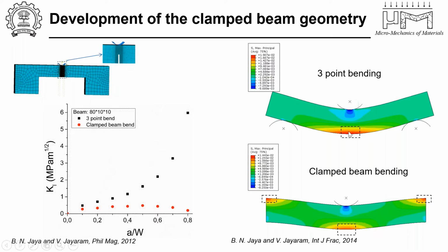And then we realized that the stresses that concentrate at the tensile edge for a 3-point bending now have 3 different positions or locations to concentrate in. So that's the center and the 2 edges where we clamp the specimen. So this gave us a clue about why there is such a large difference as you increase the crack length.